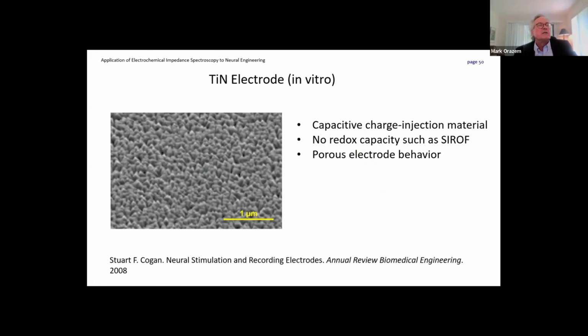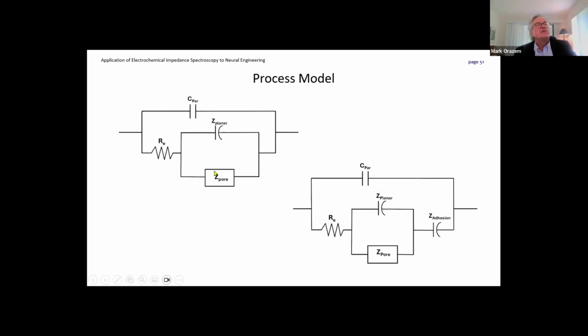from this. So from this system, we found 2 models that worked reasonably well. One was very much like what we saw for the SIROF electrode in the first example: one with a flat surface and then with a porous electrode behavior. But in this particular case, we needed to take into account the capacitance of the leads. But when we fit this model to the data, we did not get a really great fit. And the comparison of fit to data suggests that we need something in series. And so if we put a constant phase element in series, we get a much nicer fit to the data.